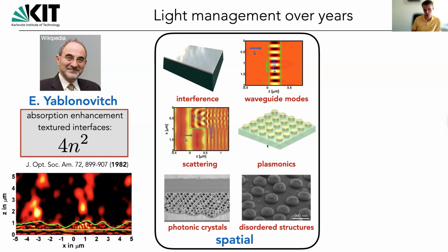Or people also considered metallic structures exploiting plasmonic effects in solar cells, where nevertheless the disadvantage is always that these plasmonic structures also intrinsically absorb light, which requires overcompensating with the absorption enhancement first of all these unavoidable losses, which makes it a bit challenging to obtain a net benefit. But at least people have been looking into using these kinds of devices in specific cell geometries.